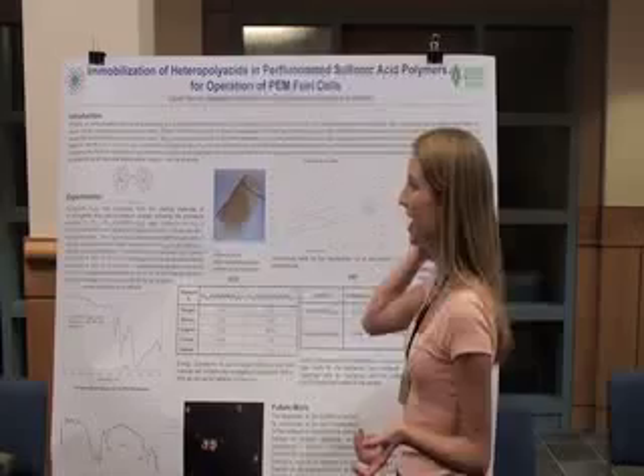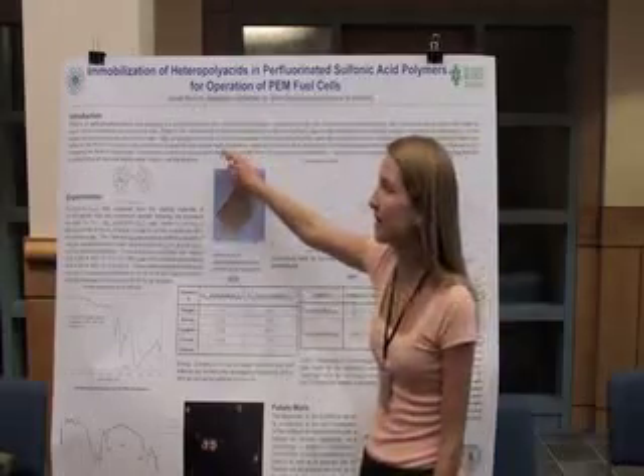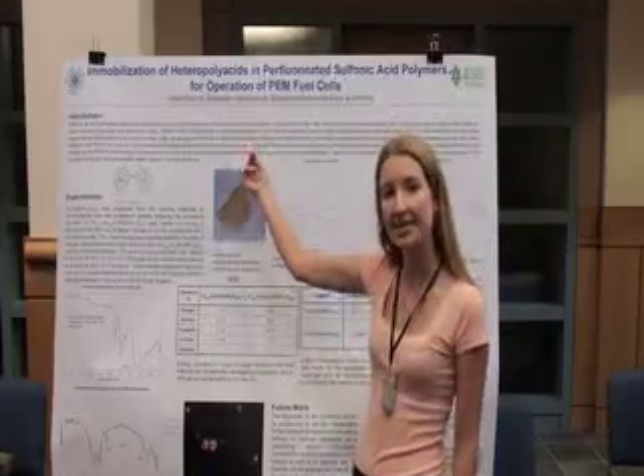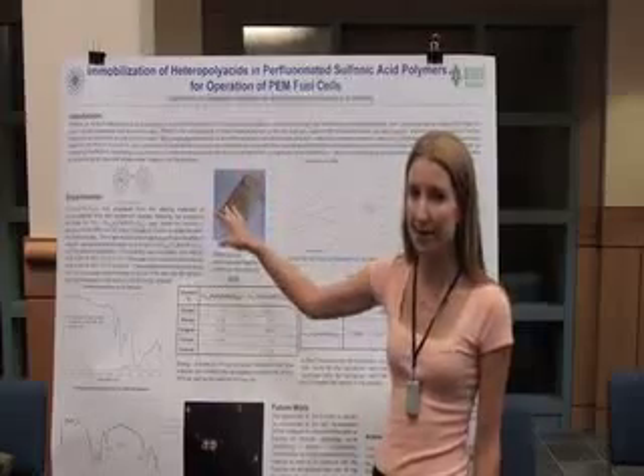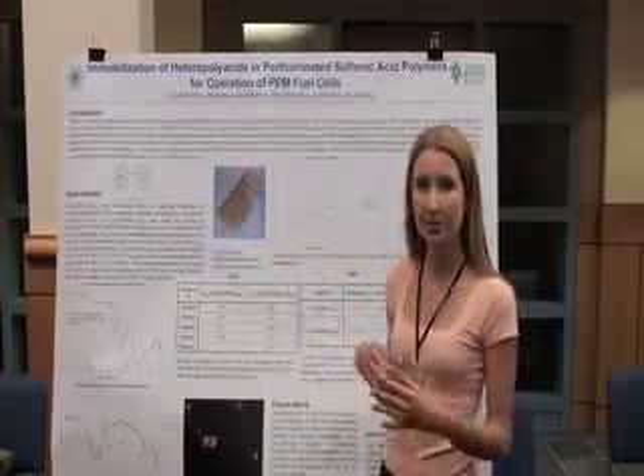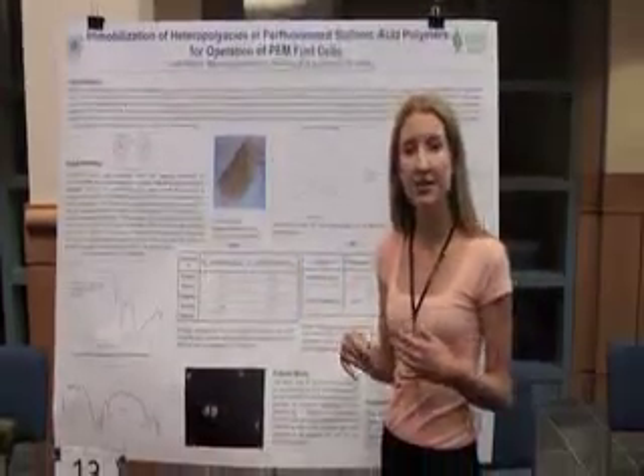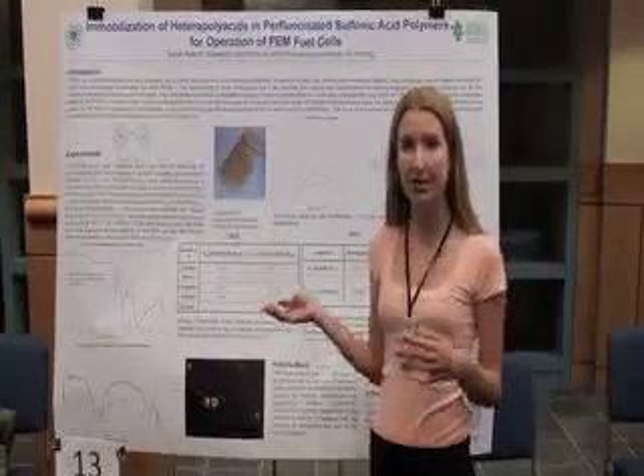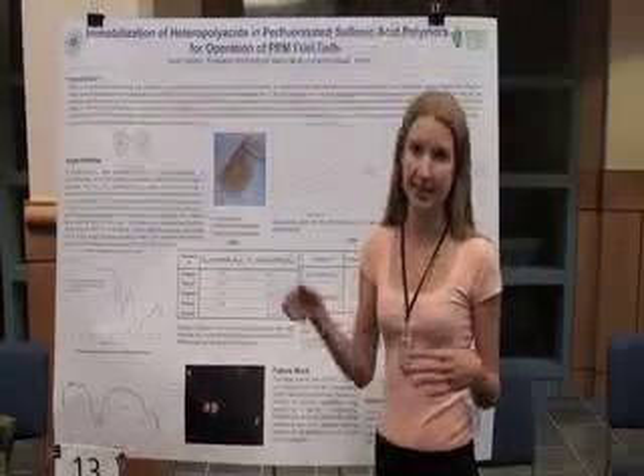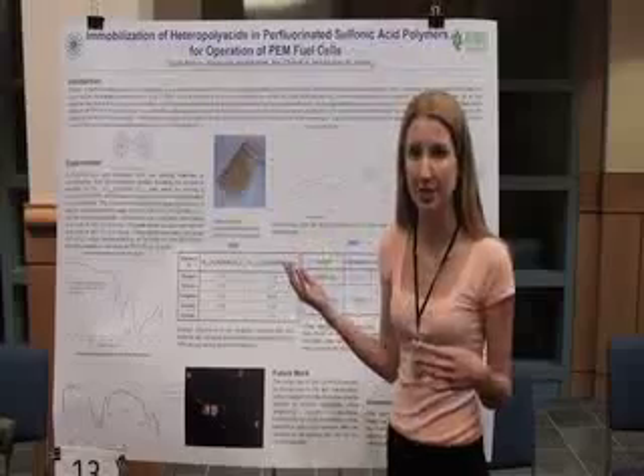What we can do to help with that is substitute inorganic heteropolyacids, which are superacids, into the PFSA ionomer. By doing this, we change the morphology so that instead of having to use water channels to transport the protons, we can have a hopping mechanism. So you can run them at higher temperatures.